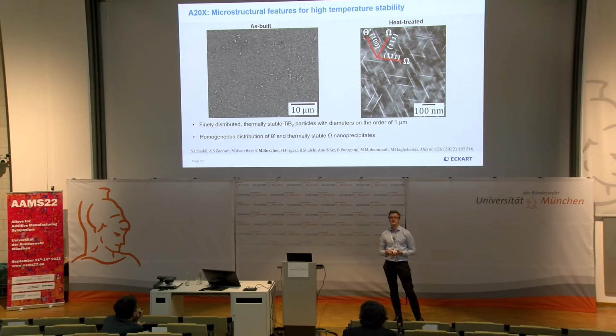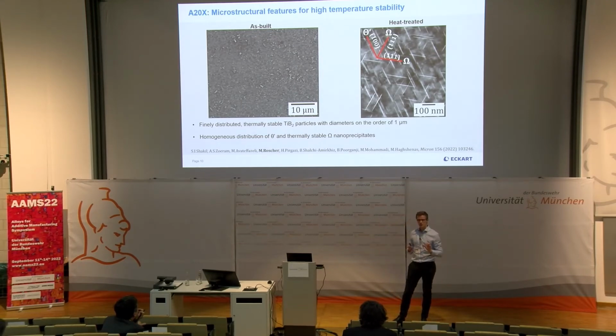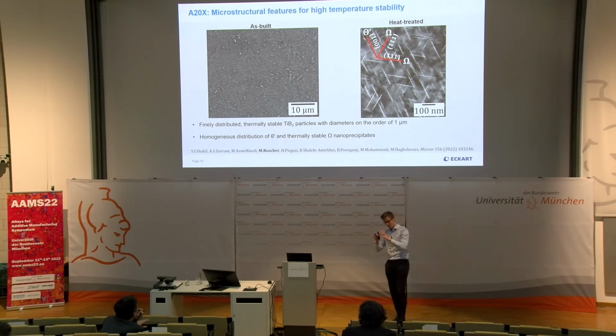This phase you only get in aluminium copper alloys that contain some magnesium, not too much. And this phase is especially promoted in alloys containing magnesium and silver. Omega phase is the most potent strengthening phase in 2000 series alloys that do not contain lithium. With lithium you can get even higher strength. But moreover, it is also considered to be the phase with the highest thermal stability among the types of nanoprecipitates we can choose from in 2000 series alloys when designing microstructure. So this contributes to the good high temperature properties.